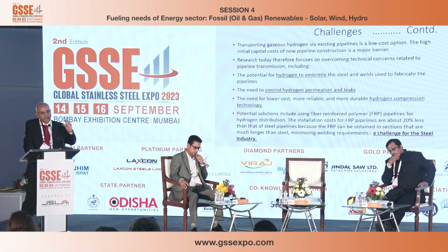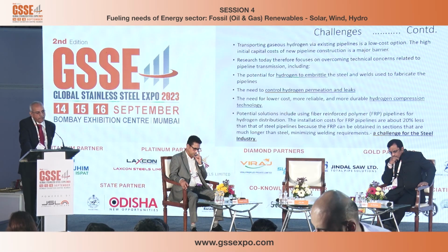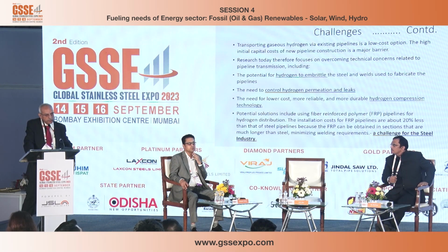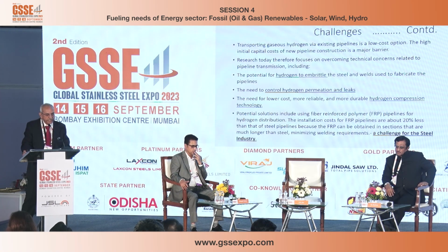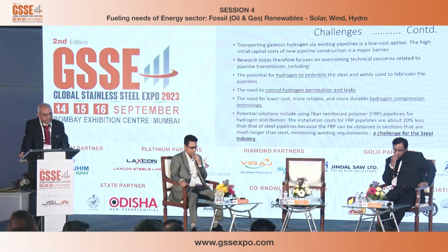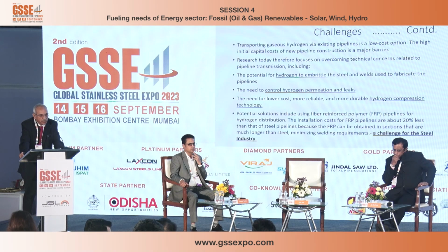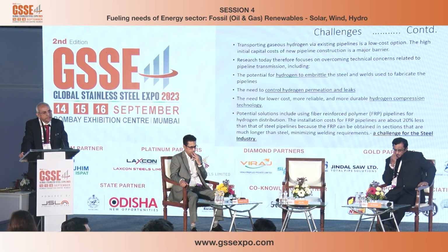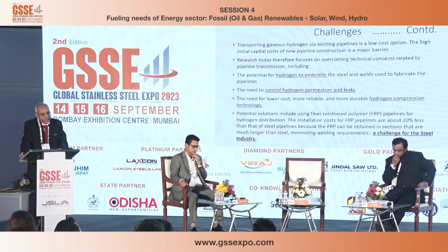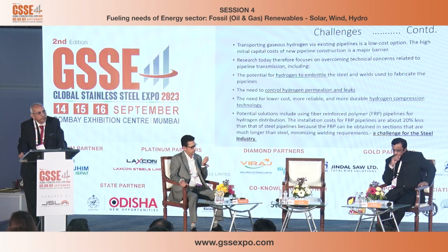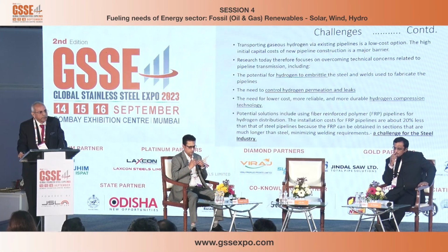As we have seen, hydrogen is required to be compressed to 11,000 psi, so we require higher compression technology. Potential solutions include using fiber reinforced polymer pipelines for hydrogen distribution. The installation cost for FRP pipelines is about 20% less than that of a steel pipeline because the FRP can be obtained in sections that are much longer than steel, minimizing the welding requirement. This is a challenge for the steel industry: how do we substitute ourselves and promote ourselves in order to transport large-scale hydrogen.